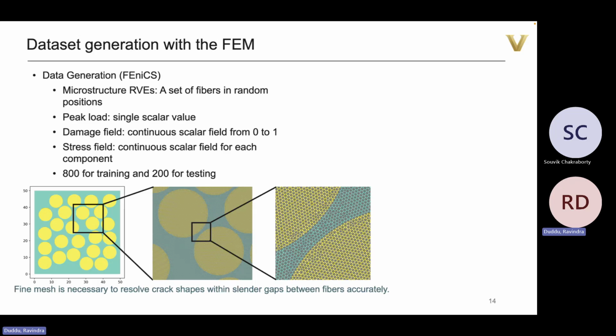So we randomly seed the centers, and then we make sure that the fibers are not overlapping and have some distance between them. And then once we do that, that gives us one realization. And we can do that many, many, many times randomly, and we can get 1,000 different microstructures. Fiber radius is the same, material properties are the same. The only thing that is changing is the centroid location of each of those fibers.